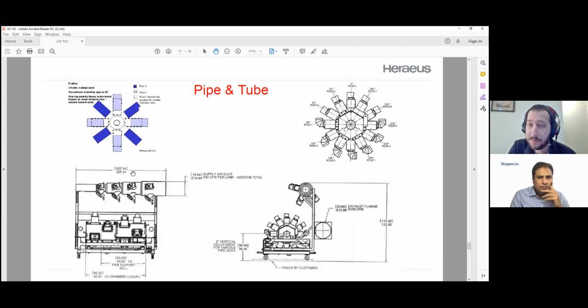For pipes and tubes, we have very complex sorts of curing systems, curing light shields. This is an example of an 8-lamp or 10-lamp system. Basically, you have a long tube or pipe, and you have to put an anti-corrosion coating on the outside of it. How do you do this? Well, you spray coat the entire exterior of the pipe, and then you pass it through a UV chamber with UV lights on all sides of it. And the UV is able to uniformly irradiate the entire outside of the pipe. And what comes out at the end is a dry, resistant, protected coating on the surface of it.